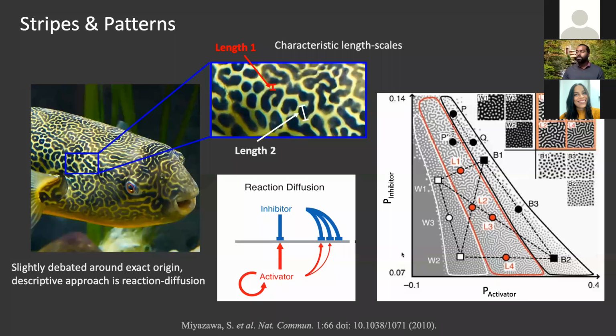And if you start to map them out and vary the parameters of the activator and the inhibitor, you start to get this phase diagram where you see these opposite phases, extreme opposites, from the gray to the white on one hand. And then you can start to have these spots or inverse spots, or in the middle, this labyrinth pattern. So this starts to match up with what we're seeing in this pufferfish. To me, the labyrinth pattern is interesting. It has a really high surface area, and sometimes surface area can be really valuable, say if you're designing a battery or a number of other systems.